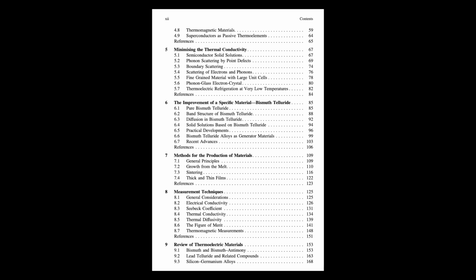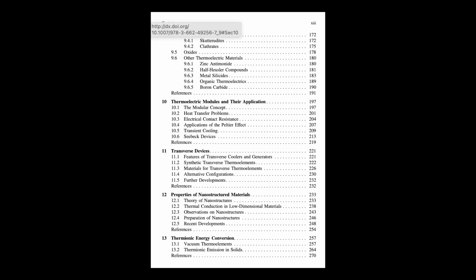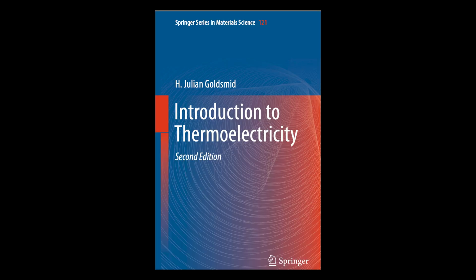What's this constitutional supercooling issue during growth? Yeah. That can happen when the solidifying material pushes impurities out into the liquid right at the interface. This impurity pile-up lowers the melting point of the liquid right there. If the overall temperature gradient isn't steep enough, the liquid ahead of the solid can actually get colder than its local melting point. It becomes supercooled. This can mess up the smooth growth, cause defects, non-uniform structures. Bad for performance. You need the right temperature gradient and growth speed to avoid it. The book even shows a diagram for bismuth alloys.